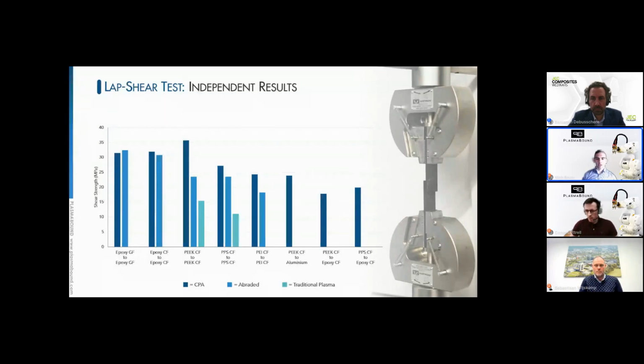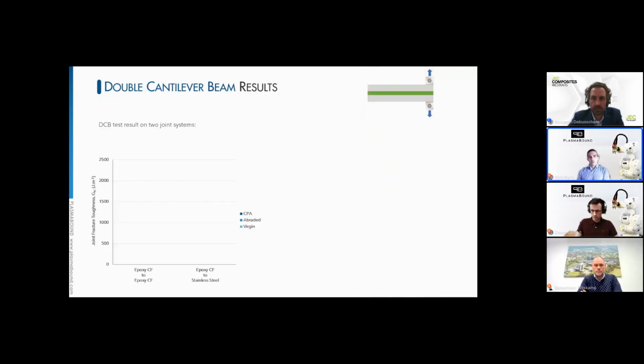And when these were tested in shear, or essentially a lap shear setup, they caused epoxy substrate failure. So the epoxy CF started to pull apart. And that is the reason why they're limited at around 18 to 20 megapascal, because it was the epoxy CF substrate that became the failure mode in these tests. So those are the lap shear tests, which are very common within the industry.